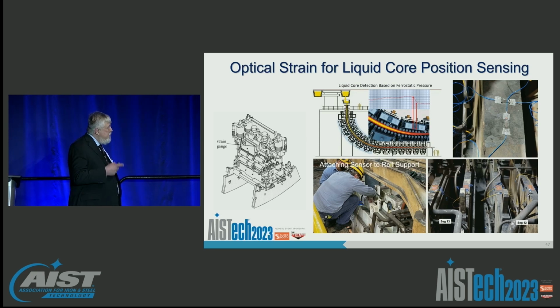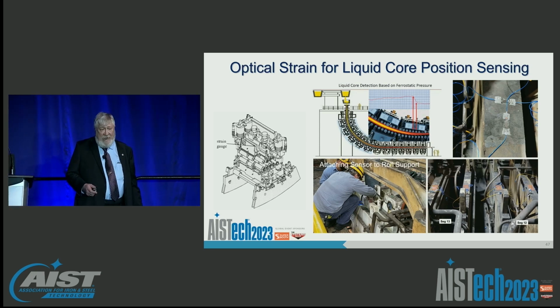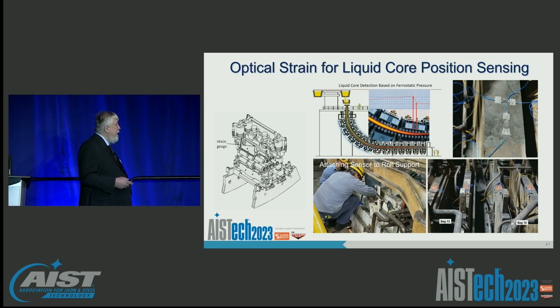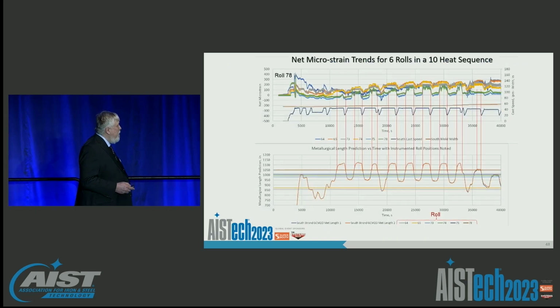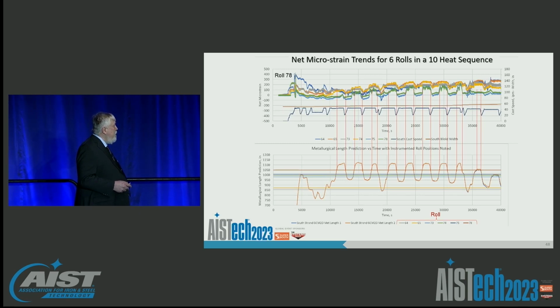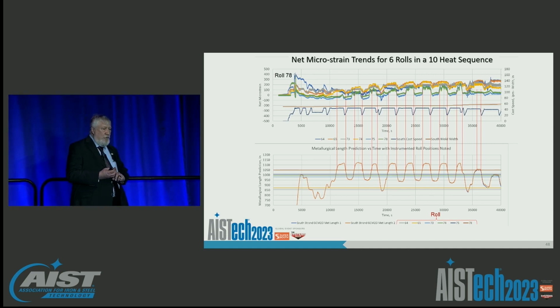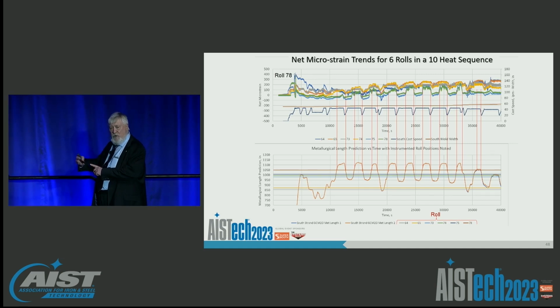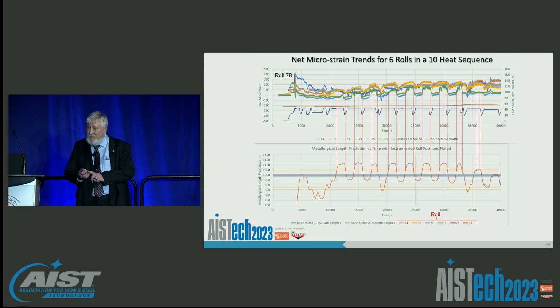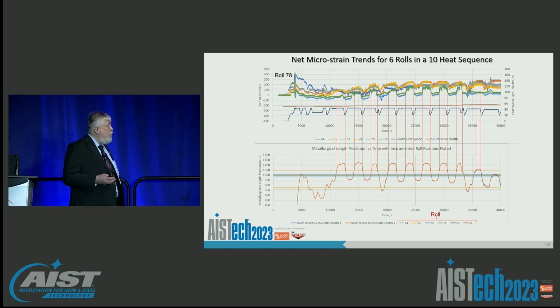And so it's pretty trivial to put on. In fact, these particular sensors were glued on the surface after cleaning with acrylate cement. And they actually produced very nice signals. In fact, we've been able to demonstrate this on a continuous caster, and have actually been able to use their internal digital twin model of the liquid core position and compare the strain measurements and actually show exceptional correspondence.